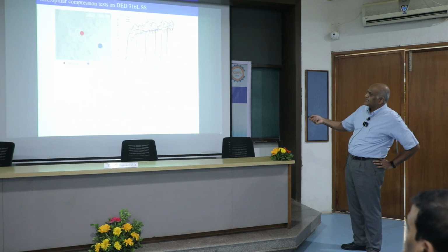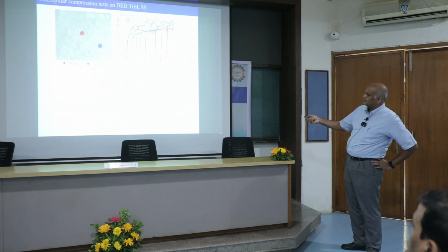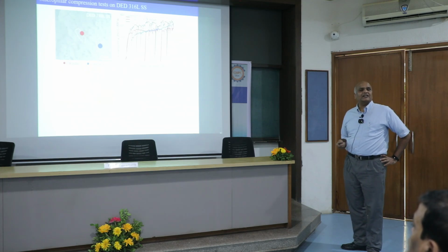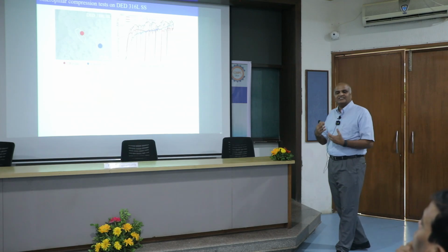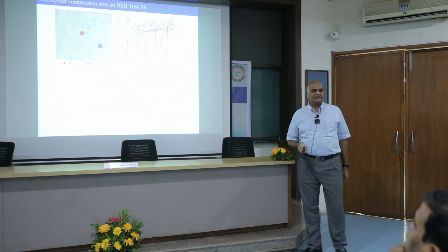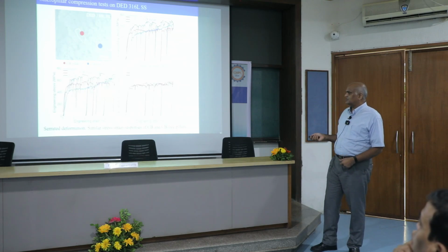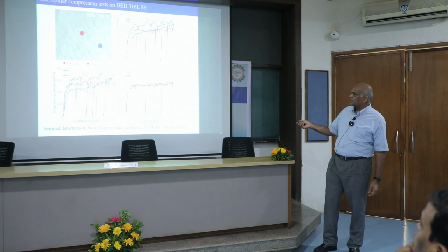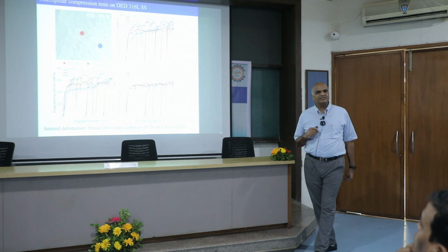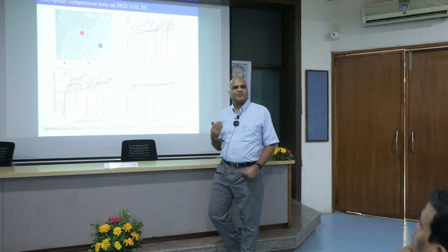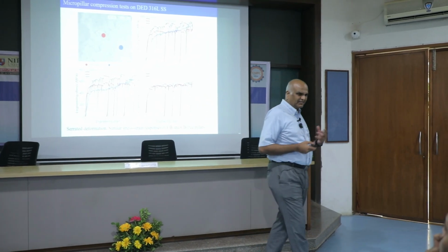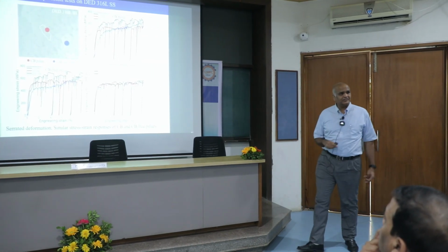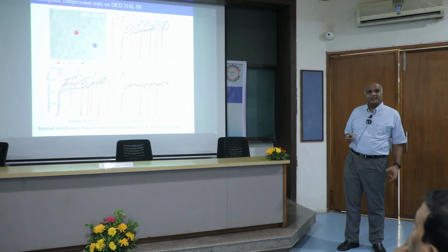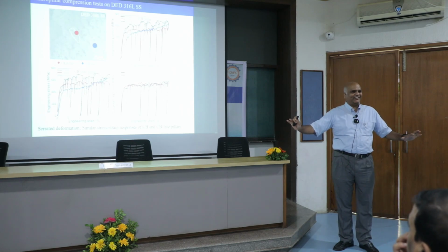For example, we can make pillars in such a way that there is a cell boundary in this red pillar, whereas this blue pillar doesn't have any cell boundary. So we can specifically check our hypotheses. We basically see that whether you have a cell boundary or a cell-boundary-free pillar, the responses are similar. That means these cell boundaries are not obstructing dislocation motion. I can send you the papers, or you can go to my Google Scholar page; we published something like 150 papers in the last 5-6 years on this.